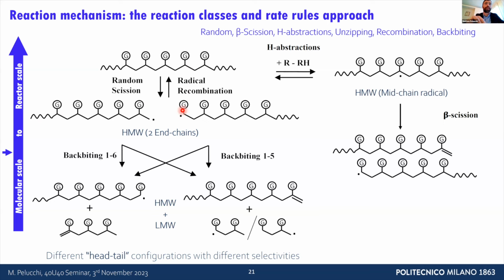This, of course, can go back. You form a radical. This radical can isomerize, and this backbiting reaction has a huge impact on the product distribution. Or you can form a radical from the chain backbone of the polymer by doing an H abstraction, forming a high molecular weight mid-chain radical. This decomposes by beta scission. All of these fragments can again decompose, can isomerize, can recombine with radicals. The reaction classes are well defined: random scission, beta scission, H abstraction, unzipping, recombination reactions, and so on.